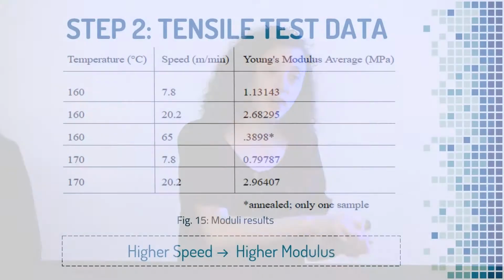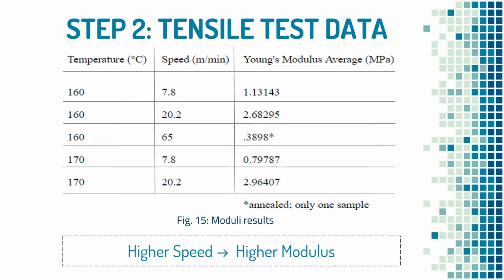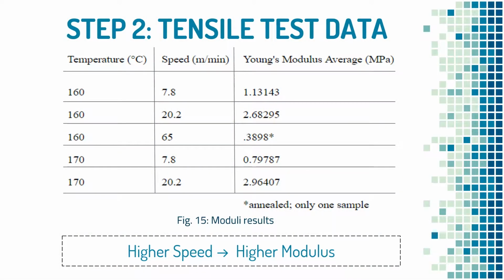So we then took the Young's moduli averages from each of the sets of samples extruded at different temperatures and different speeds, in sets of 3, and we compared them to their independent variables. Now, this is not enough data to make a true mathematical correlation between those factors and the Young's moduli. However, there is enough to state a given trend. The trend is that a higher speed, and therefore a thinner fiber, results in a higher Young's modulus, and therefore a stiffer fiber. One exception to that rule is indicated by an asterisk. This sample was annealed. Annealing is a process by which we take a fiber and heat it over a longer period of time.